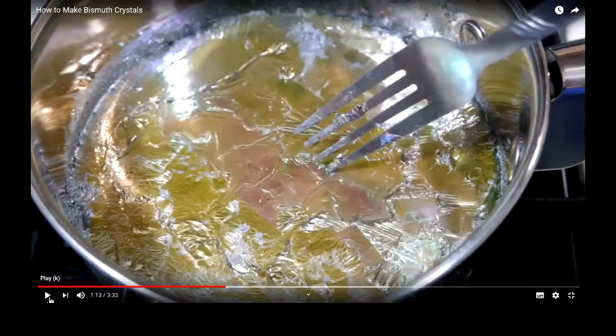If you don't scrape off that oxide layer properly, you have little oxides at the top, and that would be the nucleation site. Yep. So that's one reason. We've got oxide impurities floating on the surface which act as a nucleation site to start with.